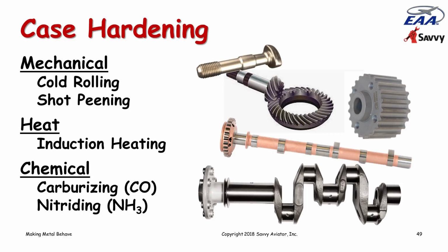Carburizing is a process where a steel part is put in an oven and heated up to a pretty high temperature in an atmosphere of carbon monoxide. And it's baked in a carbon monoxide atmosphere for a few hours. And during that baking period, the carbon in the carbon monoxide starts diffusing into the surface of the steel, turning the very surface into a much higher carbon steel than the rest of the part. And if you recall, the higher the carbon, the harder but more brittle the material is. So you start with a mild or medium steel, probably a medium steel, and then you cook it in carbon monoxide, and the surface develops this high carbon steel outer shell or outer case that's considerably harder than the interior.